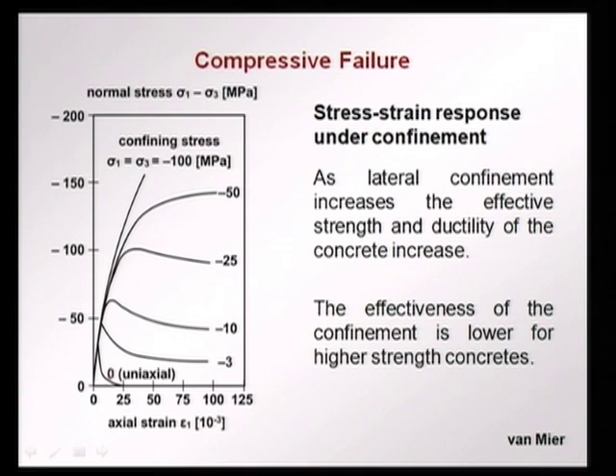So, what we find is as confinement increases, we are preventing this lateral expansion from occurring, the dilation from occurring, we are preventing this increase in volumetric strain, and therefore, we have a higher load carrying capacity because the lateral expansion is prevented. So, the load carrying capacity goes up, and also we find the ductility goes up. The concrete, instead of opening up very easily under load, the cracks do not open up, and therefore, we have higher ductility. So, we find that when we look at the stress strain behavior under confinement, as the lateral confinement increases, the effective strength or load carrying capacity as well as the ductility of the concrete increase.